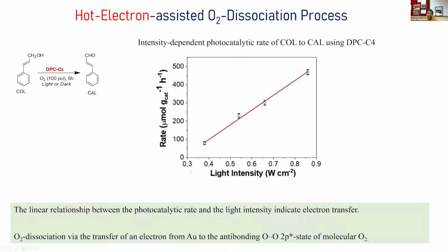So what we did, we added more and more photons onto the catalyst so that more and more hot electrons will be produced, and these hot electrons will then dissociate more oxygen, and kinetics should increase. So more photons, that means light, by increasing the light intensity, you see 0.4, 0.5, 0.6, we increase the light intensity, and you see the kinetics also increase linearly with the light intensity, clearly indicating that it is the hot electron assisted O2 dissociation that is the cause for the better activity in light as compared to in the dark, because you cannot really have electron assisted dissociation in the dark.